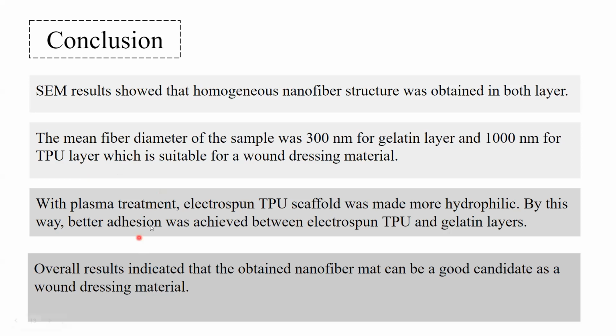With plasma treatment, electrospun TPU scaffolds was made more hydrophilic. By this way, better adhesion was achieved between electrospun TPU and gelatin layers. Overall results indicated that the obtained nanofiber mat can be a good candidate as a wound dressing material.